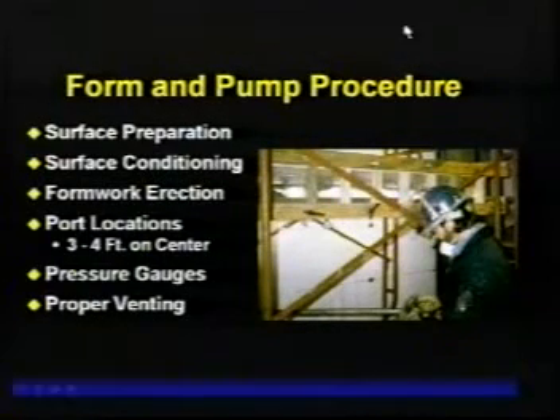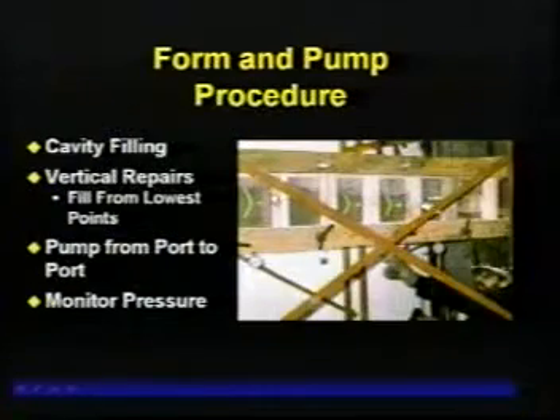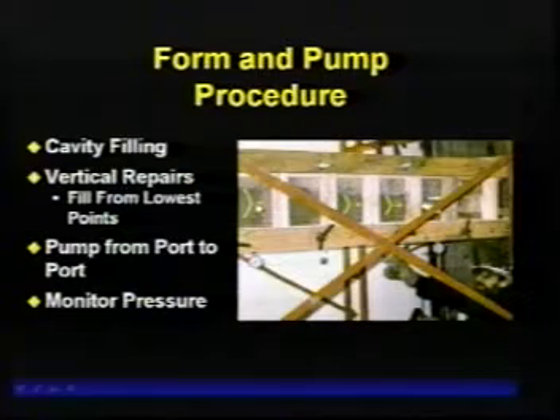These are some examples. This is the bottom of a beam, and this is the reinforcing steel, and this is plexiglass formwork, so you can actually see the material flowing through the bottom of this beam. We're filling up the bottom of this beam with this particular technique. In the first picture, the pump line is connected to the left side, and the material is moving into this form, and you can see the leading edge right here. The next slide has moved from there all the way over here, and you can see how it's building up a back pressure as it's moving to the other end of the beam. And as it builds up the back pressure, it starts to push it up against the existing substrate, encapsulating the reinforcing steel.